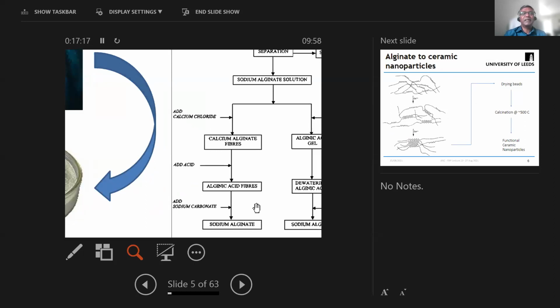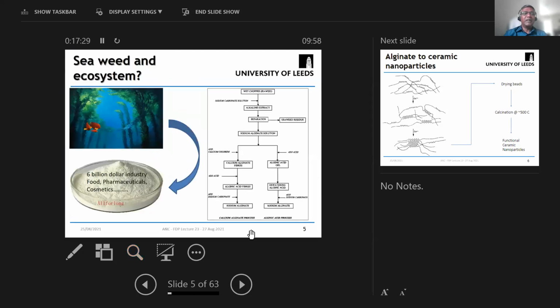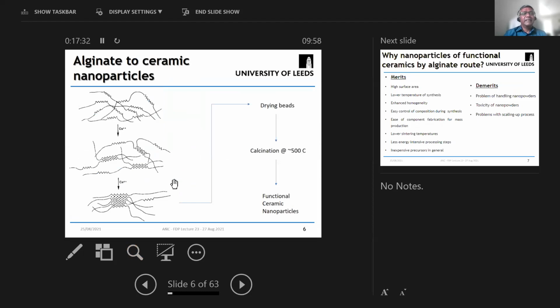So calcium chloride, calcium ions, they ion exchange with sodium very easily in alginic acid, sodium alginate solution. So what happens during the ion exchange process is that sodium alginate is a runny gel, because it has linear polymeric chains of glucuronic acid and manuronic acid. So these squiggly bits are the polymeric chains of glucuronic acid and manuronic acid, and calcium is a divalent.